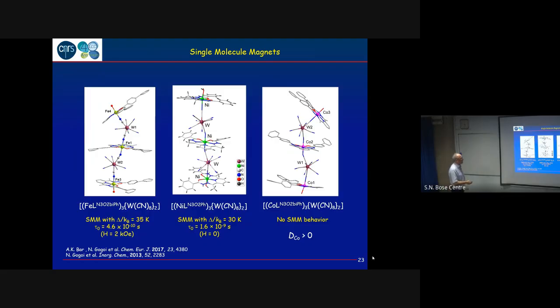If you do the same with cobalt, you have the same structure, but you have no single molecule magnet behavior, simply because the cobalt is not allowed to, because cobalt has planar anisotropy, positive D, whereas the iron or nickel has a negative one. So everything is right, everything works like it was expected.